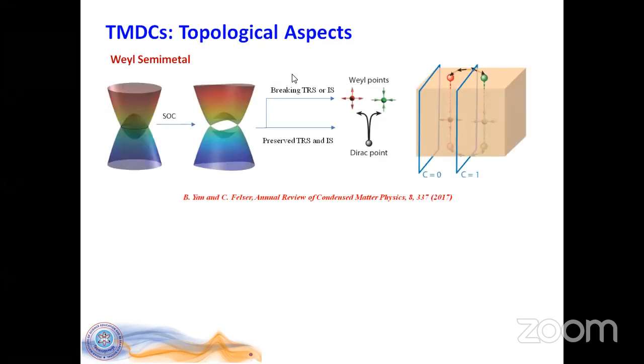Now, the other topological phase which is also interesting for our discussion today is the Weyl semi-metallic phase. Once we take care of the spin orbit coupling, we saw the band inversion, and when we think of preservation of the time reversal symmetry and the inversion symmetry, one basically gets the Dirac point in the system. On the other hand, if one of the time reversal symmetry or the inversion symmetry is broken, it gives rise to Weyl points. And that's where the other interesting phase comes up.